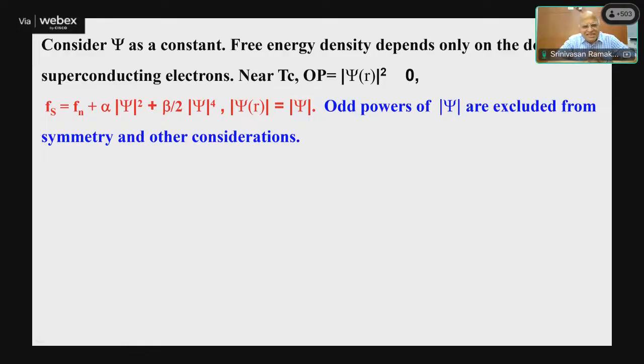Initially they considered psi as a constant. So the free energy density depends on the density of the superconducting electrons. What they said was the free energy of the superconducting state is the free energy of the normal state plus alpha psi squared plus beta by 2 psi to the power of 4. You can see that the odd powers of psi are not here. That's because of the symmetry, because when I change psi to minus psi, this should not change, and for a continuous phase transition, that's why the odd powers are eliminated.